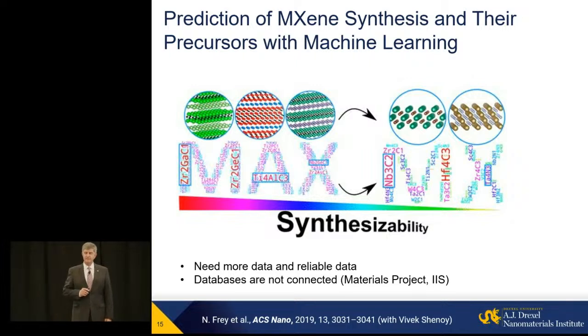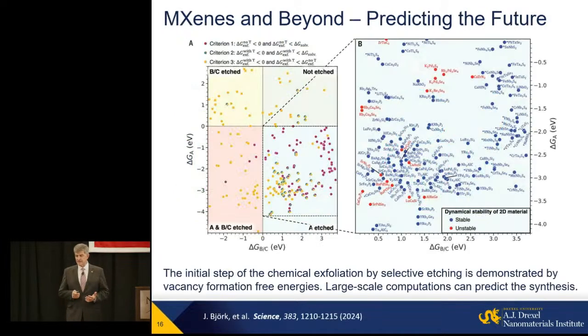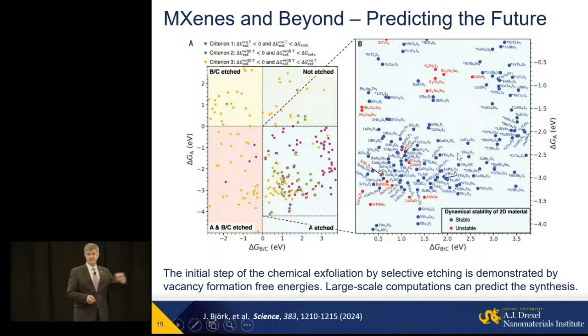We did some work with Professor Vivek Shenoy on machine learning. There are challenges. We need better data. We need databases that would include all the properties of MXenes, but it works, and there is more extensive work going on. This example is not from our work, but from very nice work by our collaborator from Linköping, Johanna Rosen, and her colleagues, where they predicted which of the layered compounds, not only MAX phases but others, can be etched, where an element can be removed, and they also made a new type of silicide two-dimensional material.